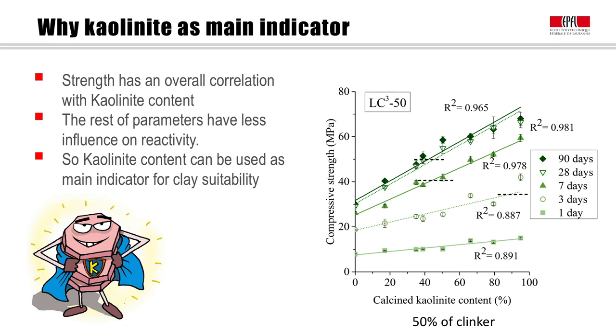Why do we talk about kaolinite? As we see here on the right, the main factor determining the development of strength is the kaolinite content of the clay. The rest of the parameters — such as surface area and secondary minerals — have relatively little influence on reactivity. So we're going to talk a lot about kaolinite content and how to measure it, because this is the main indicator for the clay's suitability.